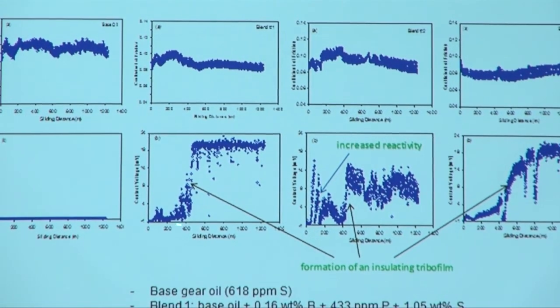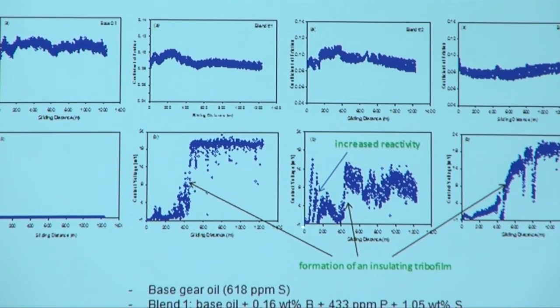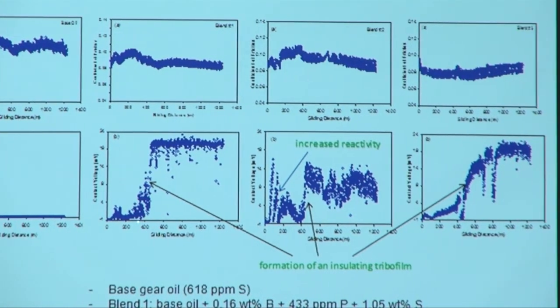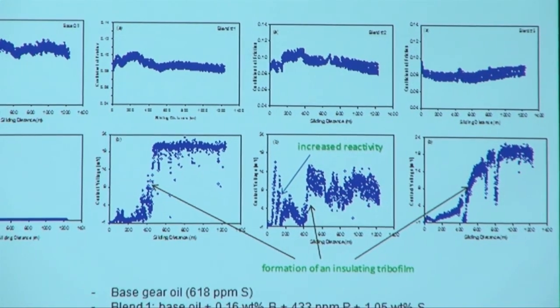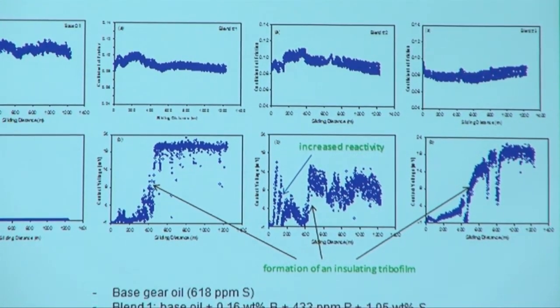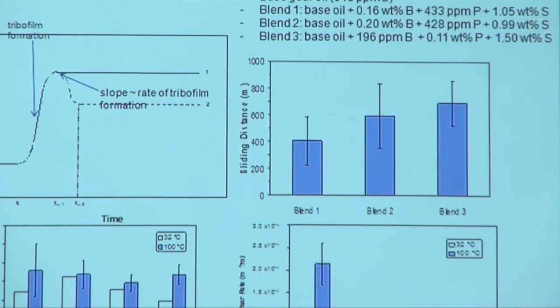So with this contact voltage, we can determine the formation of the tribofilm and how long it takes. This one takes less because it starts sooner than this, which is important because it's indicating the chemical reactivity we have between the surfaces and these additives.